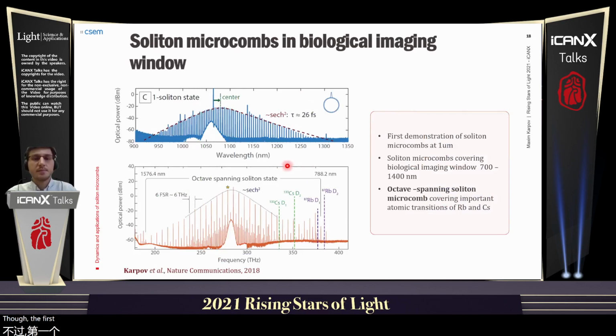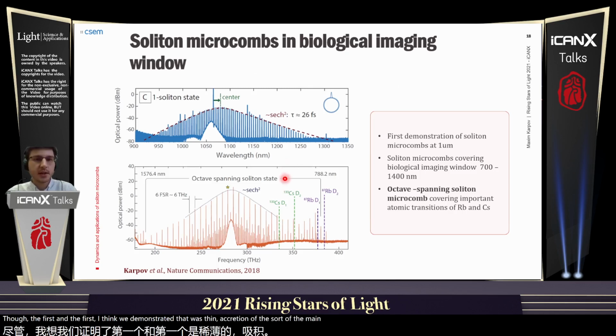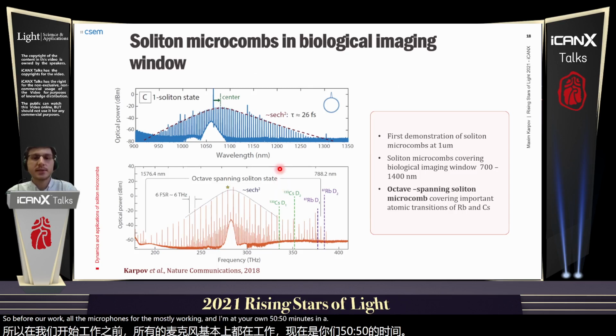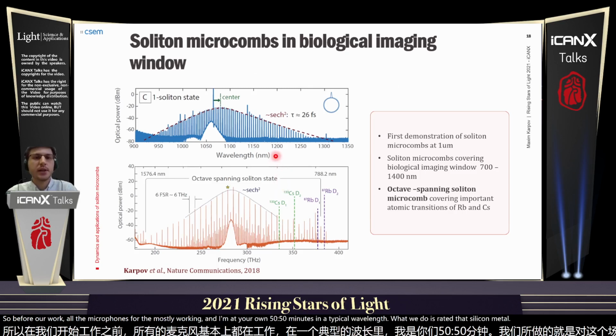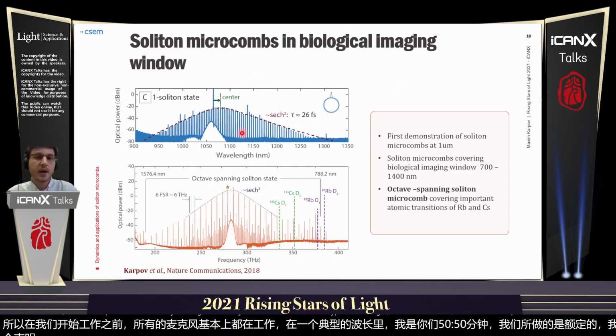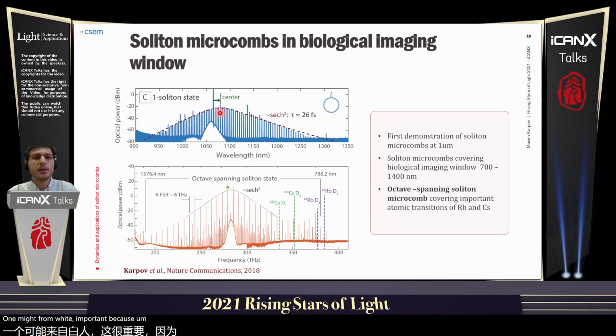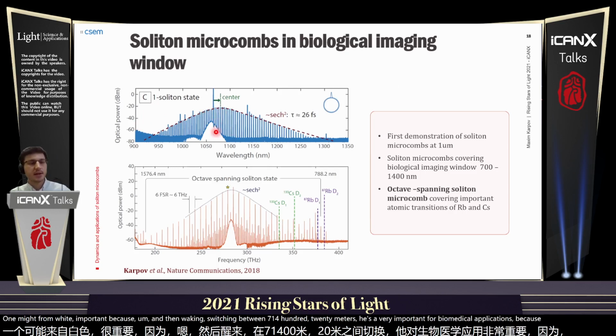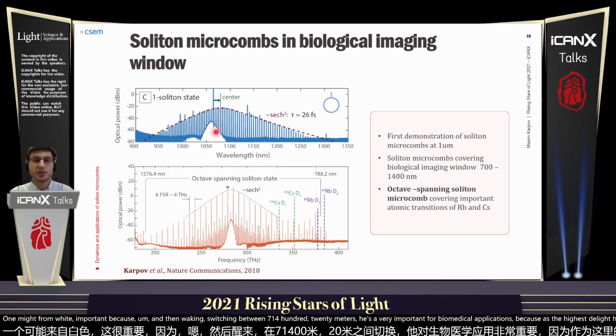So the first thing we demonstrated was the operation of the soliton microcombs in a new operational window. Before our work, all the microcombs were mostly working at around 1550 in the telecom wavelengths. But we demonstrated that the silicon nitride platform can actually enable the generation of soliton microcombs at around 1 micron. Why is it important? Because the wavelength region between 700 and around 1400 nanometers is very important for biomedical applications, because the light here has the highest penetration depths in tissue.